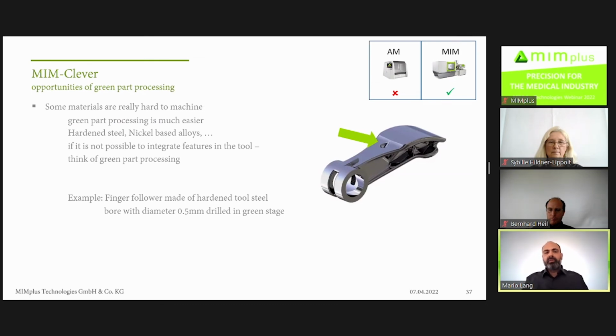MIM clever opportunities of green part processing. Some materials are really hard to machine. Green part processing is much easier. In this case, this is a finger follower for a sports car engine. The material is quite hard in the sintered stage. It has more than 50 HRC. On the other side, the 0.5 hole, which is here, is something which cannot be realized in the mold.